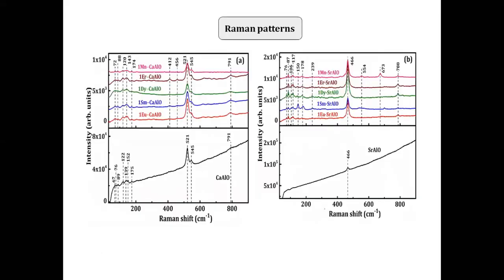And these are the Raman patterns which show the aluminum-oxygen vibration bands. And when you add the rare earth oxides, the Raman signal is greatly enhanced. So you see much stronger Raman patterns in rare earth doped